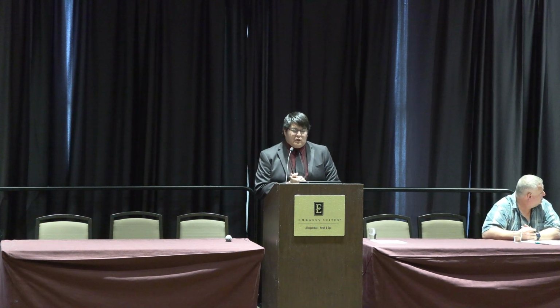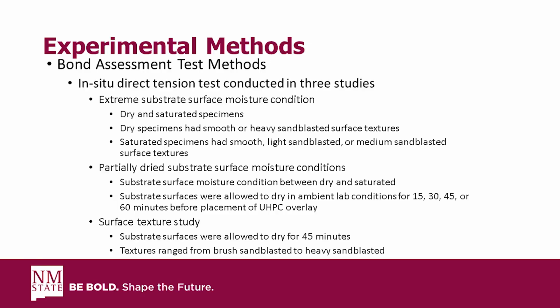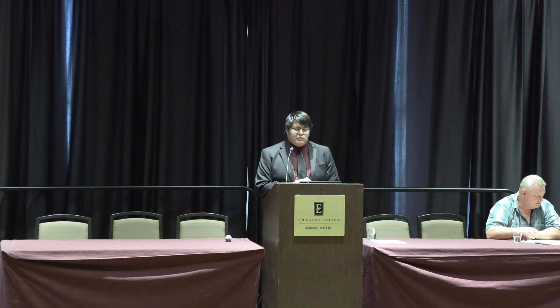Okay, so now we're going to talk about 3 parts of this study, with the first part being where we want to investigate the 2 extreme aspects. We want to look at the saturated condition as well as the dry condition, okay? With the dry specimens, we had a smooth or heavy sandblasted surface texture, and the saturated specimens, we had smooth, light sandblasted, or a medium sandblasted surface texture. And after we assess the extreme cases, we want to look at in between dry and saturated.